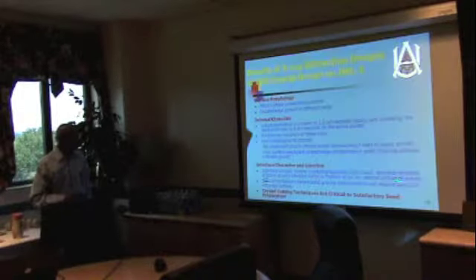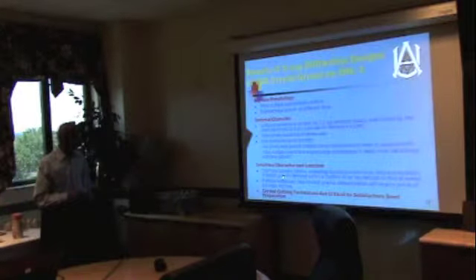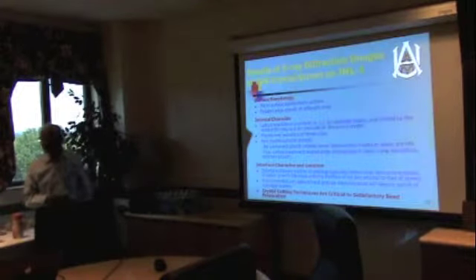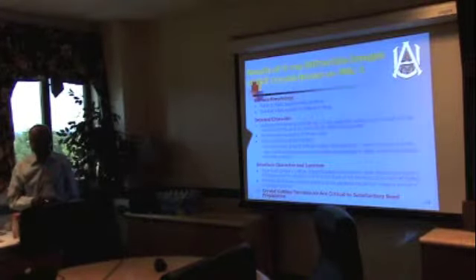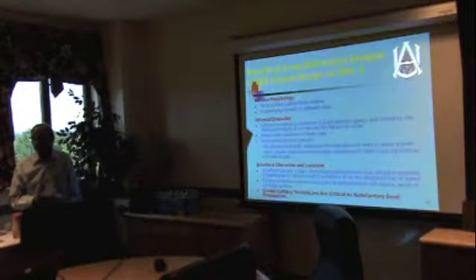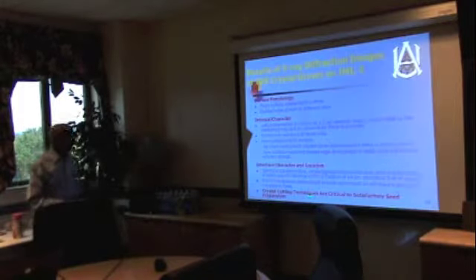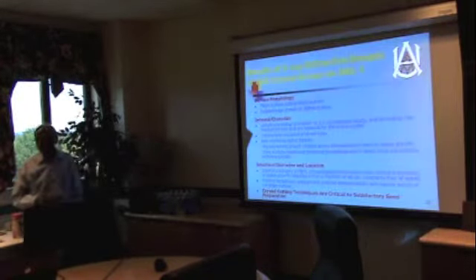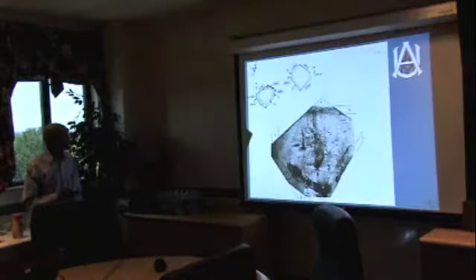Crystallographic orientation position tentatively determined, precise determination will require polishing of the cut edges. The crystal cutting technique is critical, so it is very important that you cut the crystal very nicely, because it will require sawing and then polishing it, because this actually tells us that the effect can be produced.